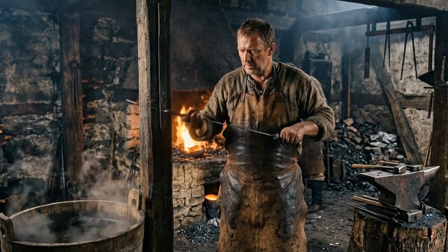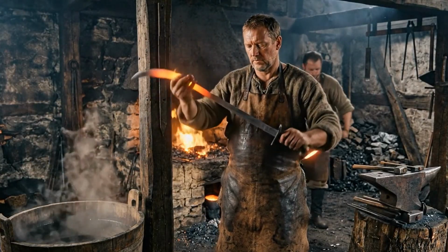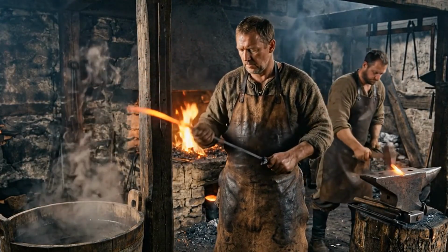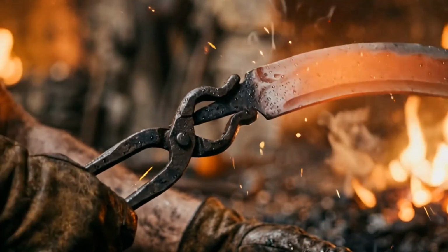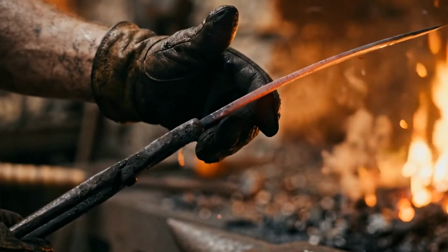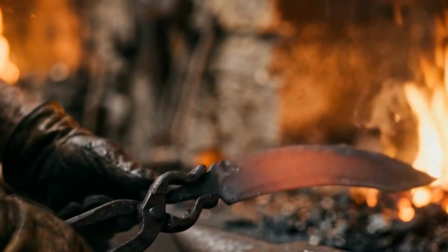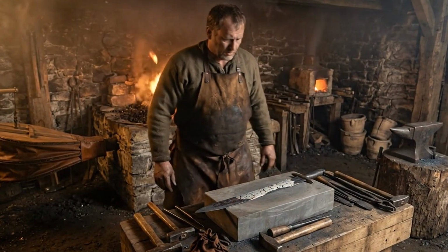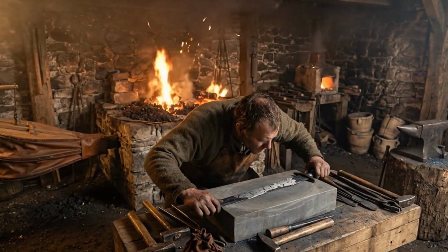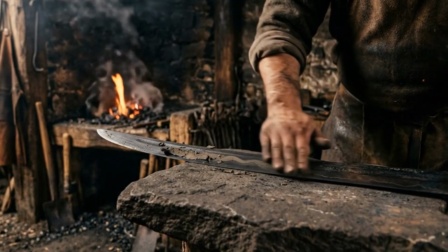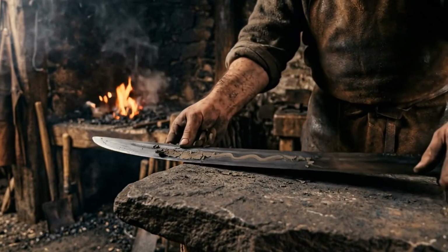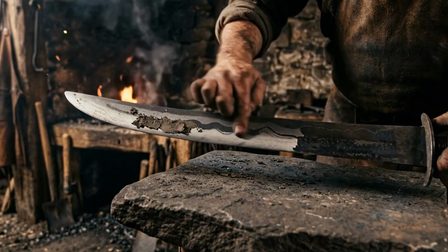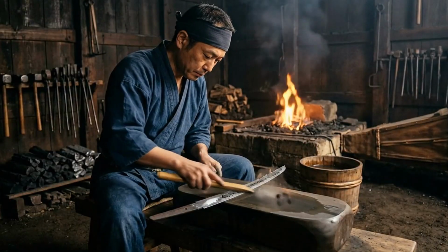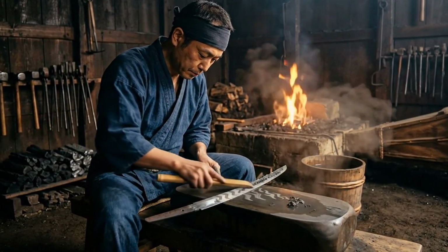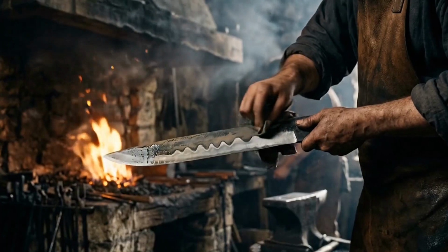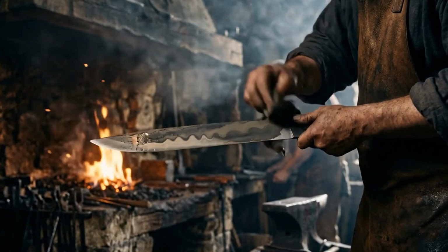The thermal shock of the quench also produced the sori, the distinctive curve of the katana. As the edge cooled faster than the spine, it contracted more rapidly, pulling the blade into its curved form. The degree of curvature was influenced by the blade's geometry, the thickness of the clay coating, and the temperature of the quenching water, variables the smith understood through experience and controlled with deliberate intent. A blade that curved too little was considered aesthetically and functionally inferior. A blade that curved too much was difficult to mount and carry.